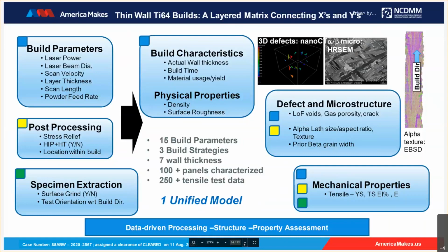In that case, we are actually putting a location stamp on it. So once we put the location stamp on it, you have the defects in the microstructure dependent on the location from where you're trying to investigate. So all your lack of fusions, gas porosities, and cracks in terms of defects, as well as the different microstructural features in terms of lath sizes, grain widths, etc., are all measured in a quantitative fashion, or it can be fed into the unified model here. And then driving out, the last step is the sample orientation and whether we are machining the sample or not.